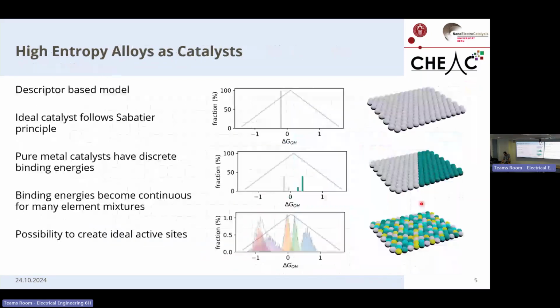And if we look at the binding energies over here, this is one I got from real DFT data. We have some active sites around the top, but we also have these other active sites, and the color now represents the metals for which these binding energies are calculated. These can be considered inactive because they are so far away. I do have a correction to the model, assuming that the second element is also participating in the reaction, but I skipped it in this presentation to make it simpler.